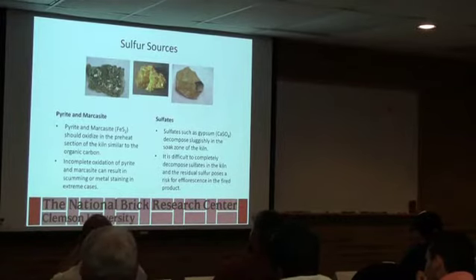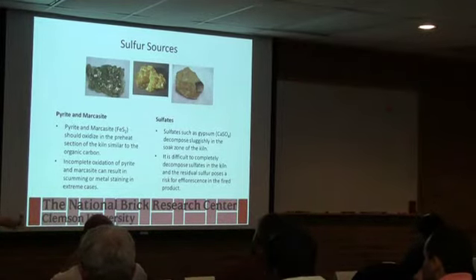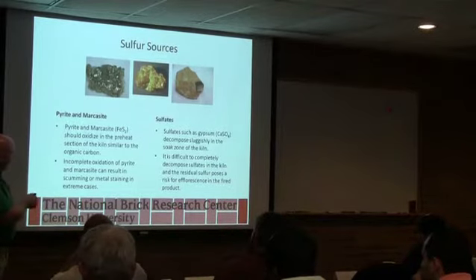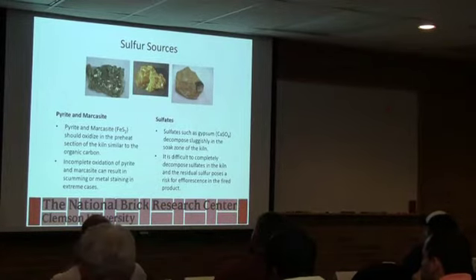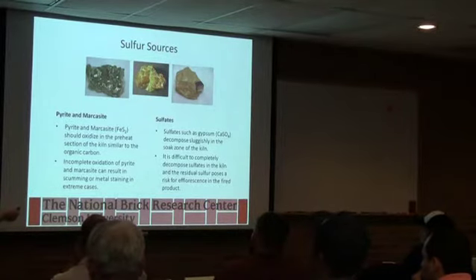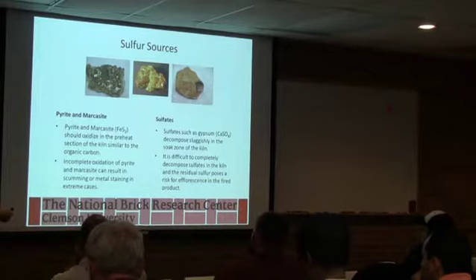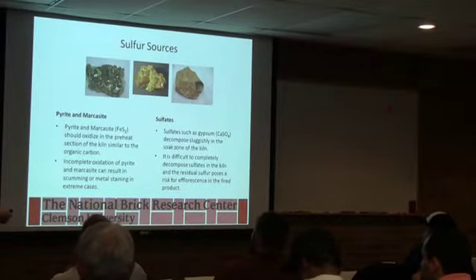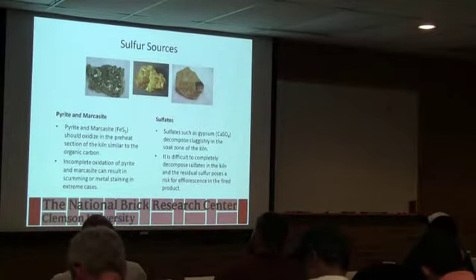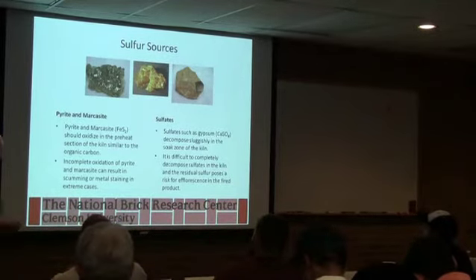It's not uncommon. I'm dealing with a situation now where it appears that the soluble sulfate content is increasing going through the kiln. When we measure the soluble sulfate of the raw material, it's got pyrite. This isn't very soluble, so we're not getting a very good solubility number. The fired brick effloresces like crazy. So we're trying to figure out why. The total sulfur number doesn't really change going through the kiln. So what's in the raw material starts out as an insoluble form, so barium doesn't really help. And then by the time we get it through the kiln, we're not really oxidizing it, and it becomes a sulfate that then causes efflorescence. So kind of interesting when you look at it.